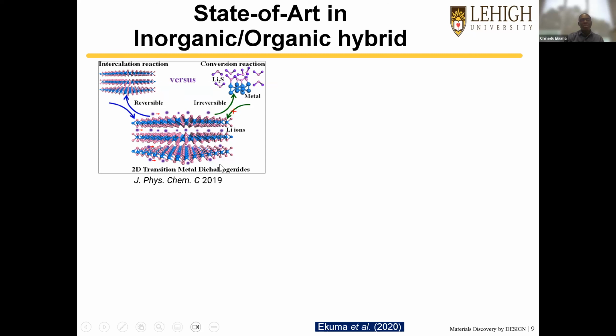A typical example is this transition metal dichalcogenide. MoS2 is like their poster child. We can take something like lithium, sodium, and intercalate between these layers. Now, there is something also unique. These gaps between these layers are intrinsic, meaning they occur naturally in these van der Waals systems, and are of the order of 3 Angstrom. So we can literally insert some molecules, ions in between those gaps that we can use as a tuning parameter. Another beautiful thing about chemical or electrochemical intercalation is that they are reversible, unlike generic approaches that are not reversible. We can insert and also remove these molecules or ions within these natural van der Waals gaps.